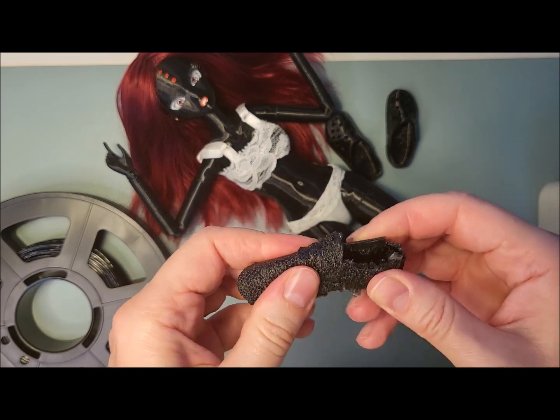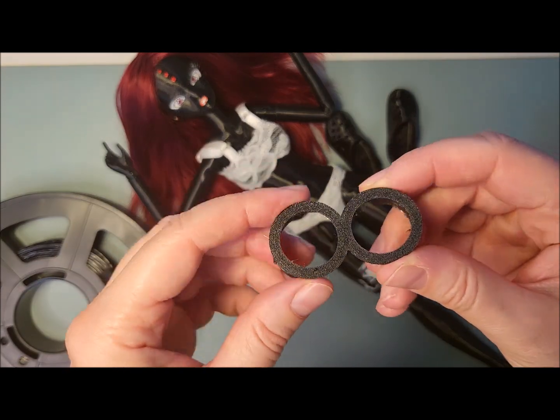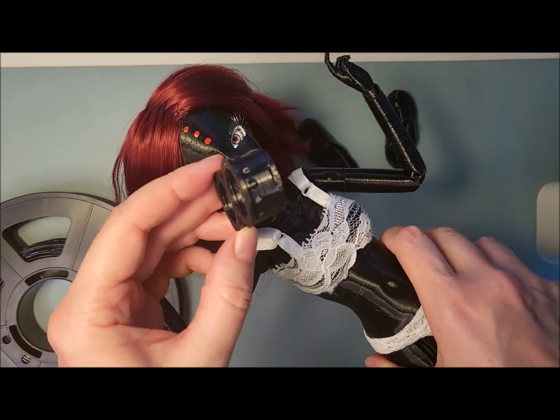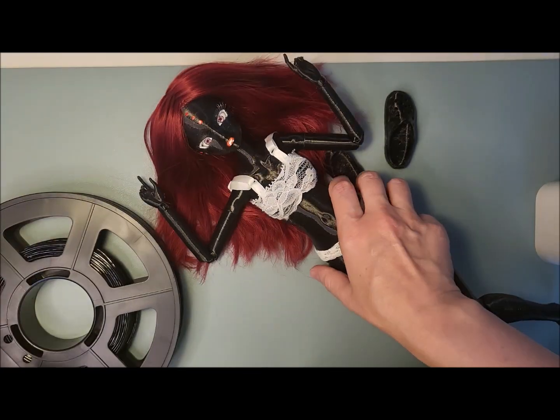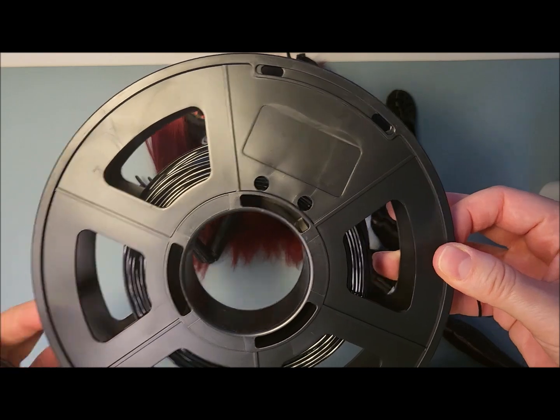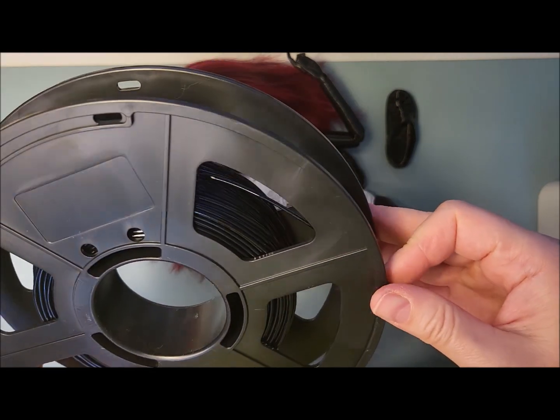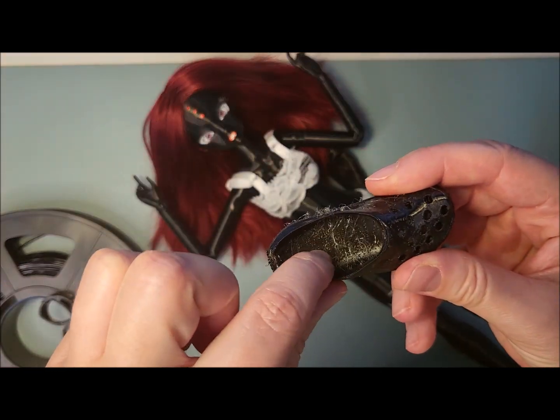I was hoping to print some shoes, but it didn't quite work. One thing that printed well were the goggles from the Minions — the holes are printed pretty decently too. It's quite a funny material because I have to put the filament in a dryer — like a small oven, a special filament dryer — every day, otherwise it attracts moisture very rapidly. If you don't dry it, bubbles start forming in the printer and it creates these funny hair-like strings.